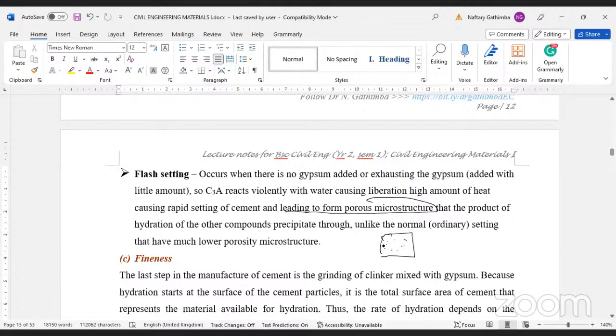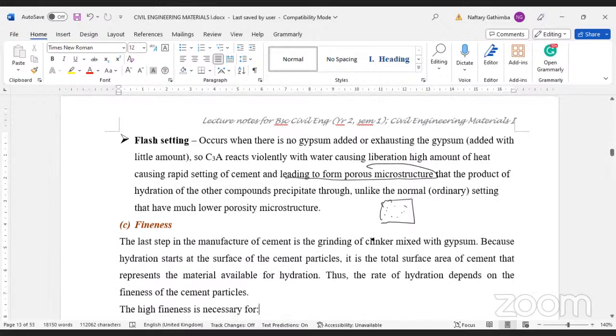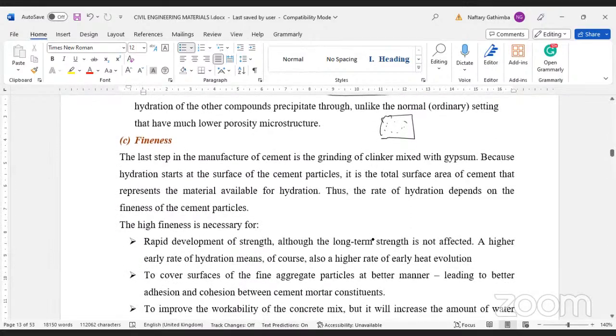Ordinarily, flash setting is worse than false setting, because from false setting you can just remix your cement paste and then you acquire your plasticity. But flash setting, if it forms, it's done. And that's why you have to stop that process. Tricalcium aluminate reacts first. You have to slow it down so that it gives time for other compounds to finalize the reaction process.